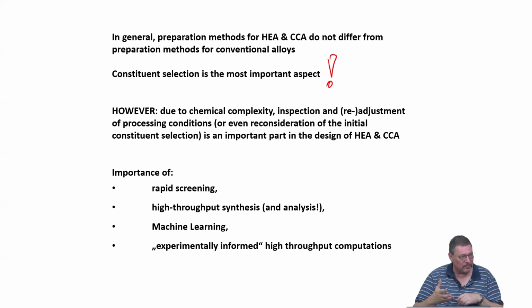You try out a certain alloy with a certain number and type of constituents. You try to make it, you look at the outcome, you see cracks have formed, or maybe segregations are there, and then some improvement must be made. So maybe you go to a higher soaking temperature, you have to soak for a longer time, you have to maybe flip after initial melting several times so that the density differences are leveled out. And only by this repeating and improving can you get the best alloy.